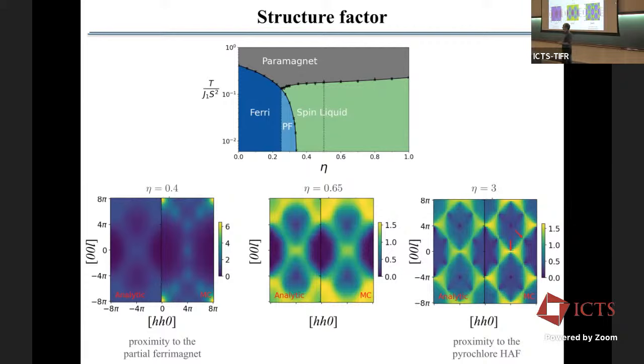Okay, you can also have some other anisotropies, I guess, even though the system is really symmetric. Experimentally you usually get also other anisotropies. It is possible to have single-ion, a second order effect. Yes, exactly. It is possible to have a local z-axis or XY anisotropy, a small one because it's manganese and it's half-filled, but it's still possible. We tried to play with the J-free coupling, but it didn't really match the experiment. So we don't expect it to be only J-free exchange. But anisotropy is a possibility. Okay, thank you.